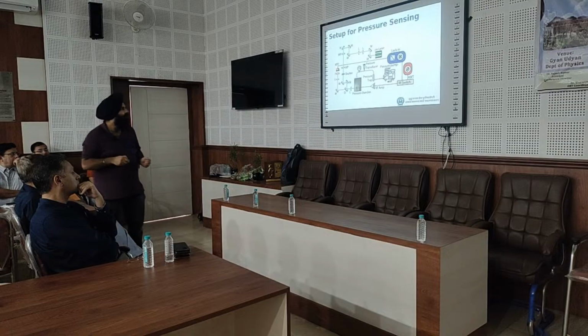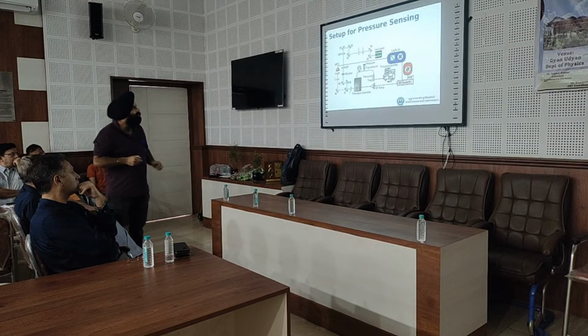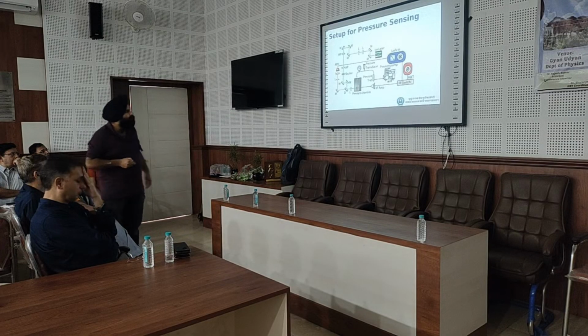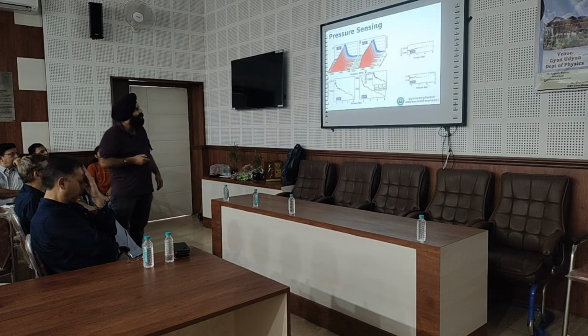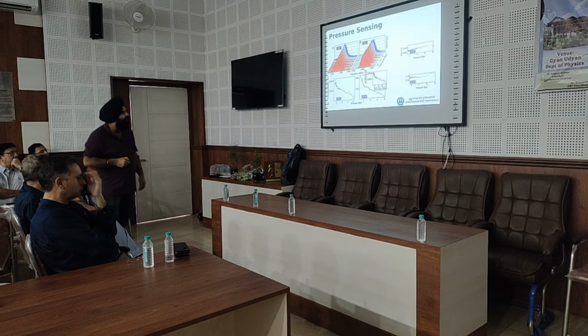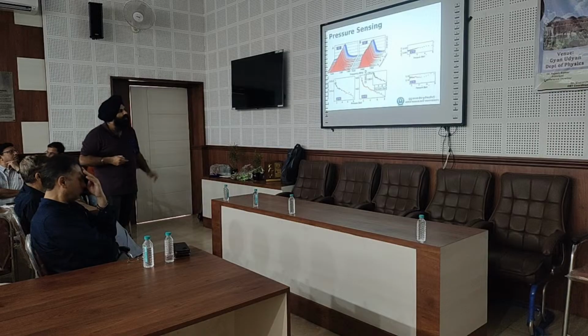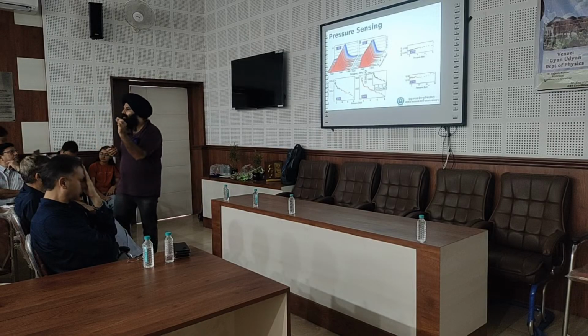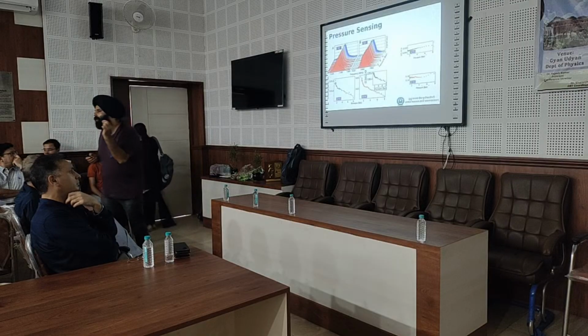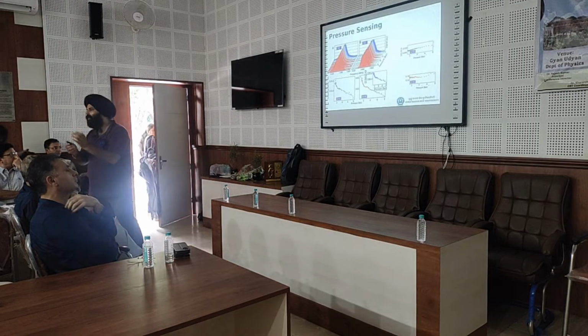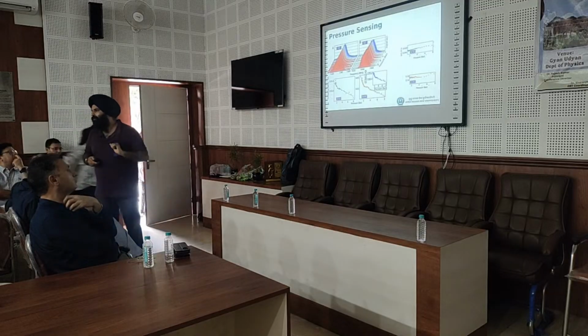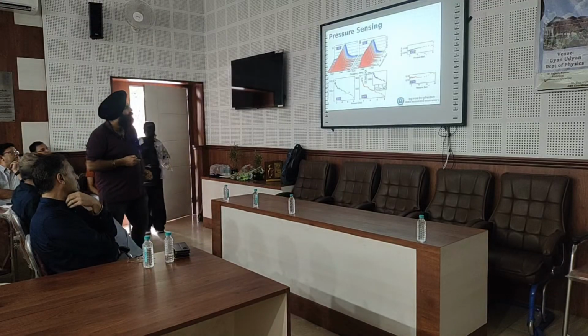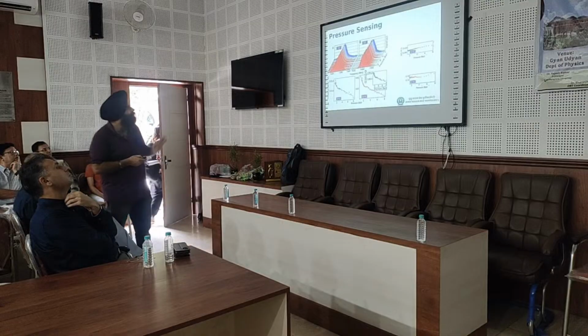It's the same pump, and the rest of the setup is the same. When we apply the pressure, again these transitions change, and you can see these peaks are changing. Because the organic crystal is very soft, it is very pressure sensitive. In diamond, it is very hard, so it is not as sensitive as this crystal. Due to that, this was a very nice result.